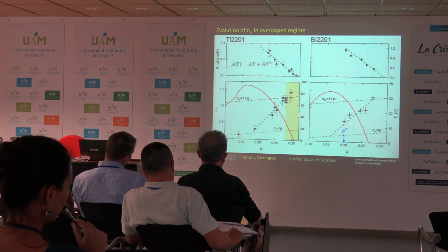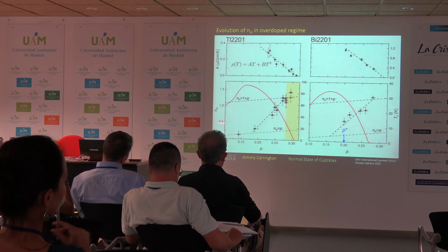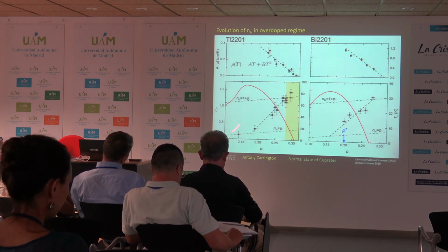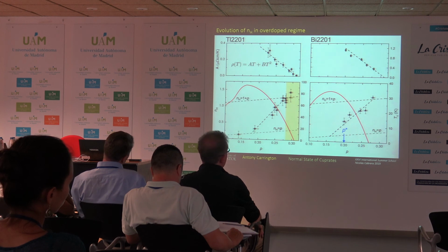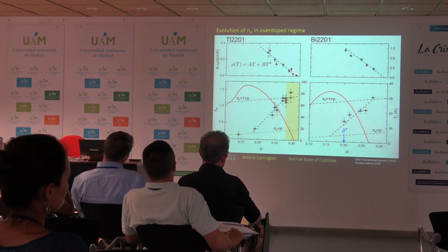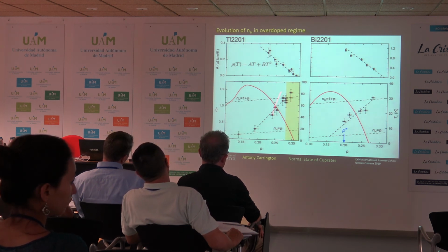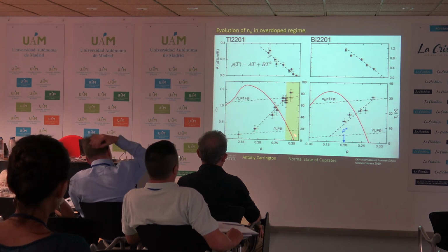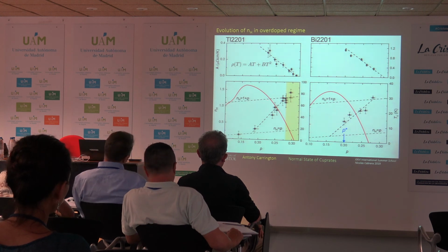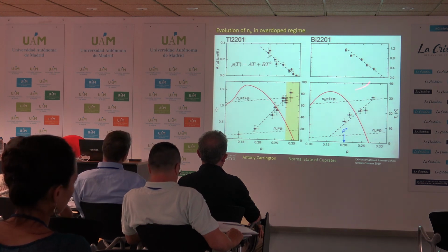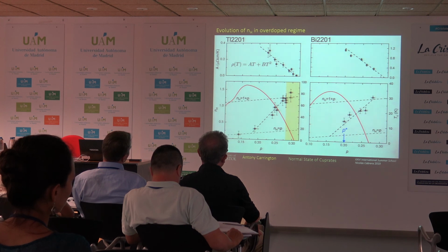So this therefore calls into question whether or not this rise in the Hall coefficient that was reported in YBCO is really linked to the pseudogap, because here there is no pseudogap. What it does seem to be correlated with is the linear coefficient in the resistivity. So this decrease and this increase seem to both be correlated with the increase in Tc as you move away from the superconducting dome. And I'll just flash up some data for lanthanum-doped bismuth-2201, which shows exactly the same thing.